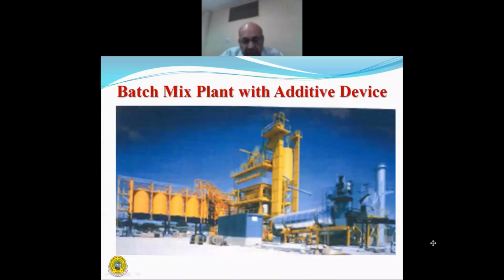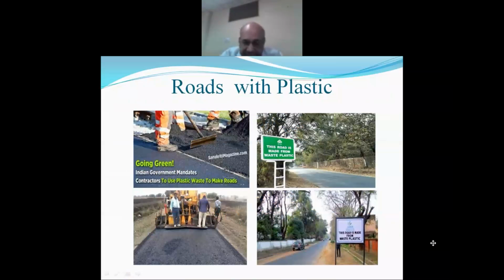So for the drum, we have two options. The drum of the drum mix plant has to be modified into three parts. One is the fire chamber, where the aggregate is heated. The second one is the chamber for shredded plastic waste, and the third one for adding the bitumen. Once the aggregate is heated on the left hand side, in the fire part, the aggregate is pushed to the middle part of the drum, where an opening is provided for adding the plastic over the heated aggregate.